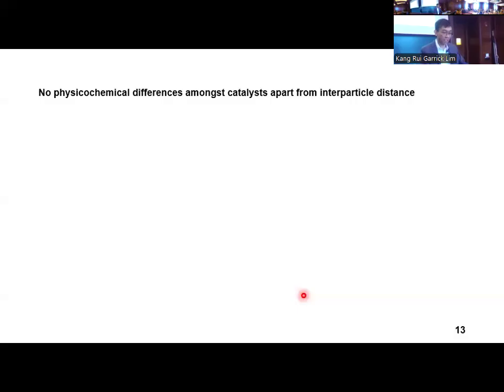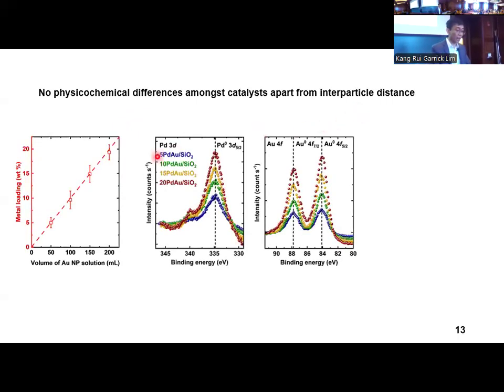Beyond the fixed nanoparticle size, we also had to ensure that all the catalysts were physically and chemically identical to each other, with the only exception being the controlled metal loading and thus the average interparticle distance. We saw that the metal loading increased linearly with the volume of nanoparticle solution added, evident from the ICP elemental analysis and the increasing XPS peak heights of both palladium and gold. Moreover, the nanoparticle composition and oxidation states were also preserved, as seen from the ICP elemental composition data and the unchanged XPS peak positions for the metals.